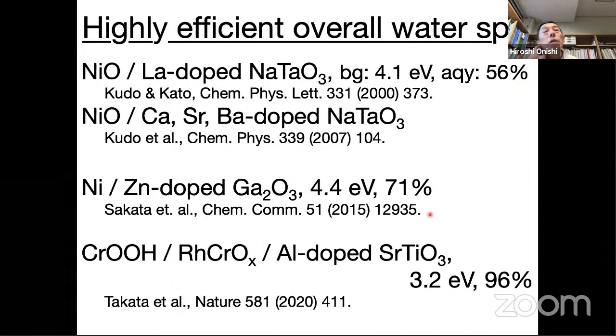And secondly, as a scientist, we recognize that metal cation doping to the host metal oxide always provided the key to increase the apparent quantum yield. Of course, Kudo-san and colleagues first prepared pristine, pure sodium tantalate as a photocatalyst, and they got some results. But later, they found that by putting a small amount of lanthanum into the host material, the quantum yield increased much. And this is also the case with other materials. Always putting some metal cations, heterometal cations, was very good to increase quantum efficiency.